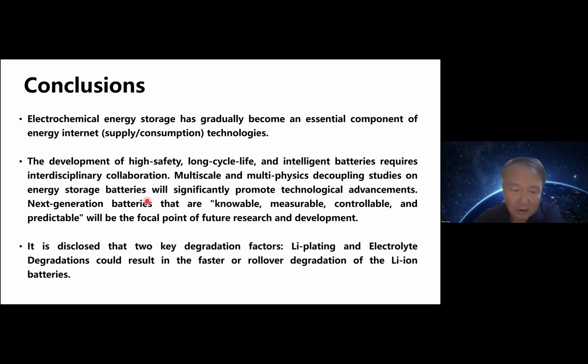So in this talk, we have shown that two key degradation factors, lithium plating and electrolyte degradation, are very important core issues for understanding the degradation of lithium batteries. They cause faster or rollover degradation of the batteries.